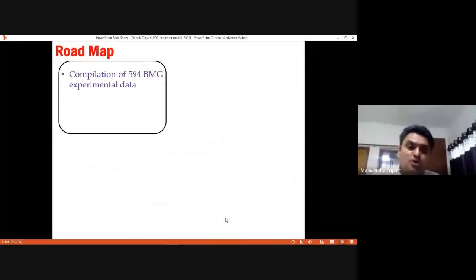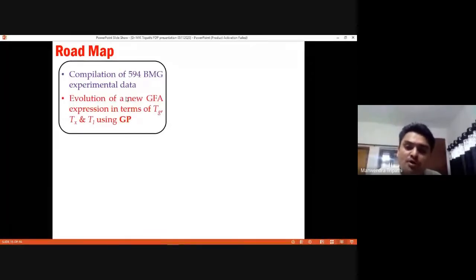The very first step, what we have done is that we have compiled the metallic glasses, and when I say BMG, bulk metallic glass, if the critical thickness is 1 mm or more, it is called BMG. Now this condition is revised. It is proposed that if the critical thickness for a particular alloy is 10 mm plus, then we should call it BMG. But in this particular case, when I say that I have collected 594 BMG data from the literature, experimental data from the literature, I have assumed BMG stands for 1 mm critical diameter. Okay, so that data we have collected. So what we can do is use this data for predicting further data.